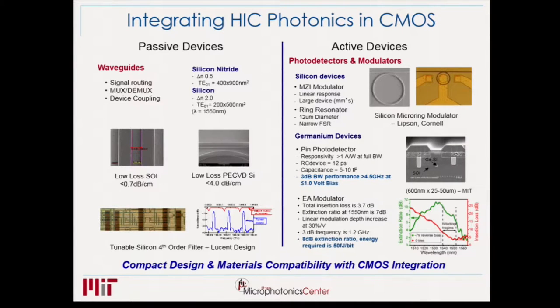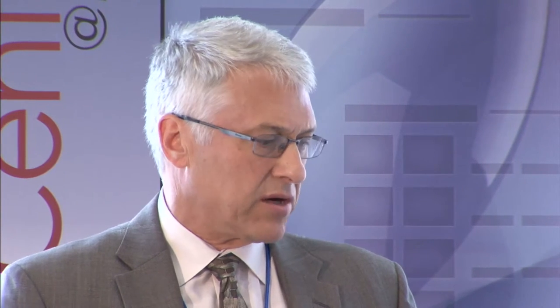The more challenging yet optimistic approach involves germanium devices. Germanium was the original transistor material, but suffered from water-soluble processing issues — germanium oxide is not a stable oxide. However, in the context of CMOS processing, we can protect germanium films and utilize its band gap at 0.7 eV, matched at the telecom wavelength of 1.5 microns. That germanium device can be leveraged as a platform device — not only for photo detectors, but for modulators and, more recently, the germanium-based laser. The scale of germanium allows it to fit within the process flow of silicon CMOS.